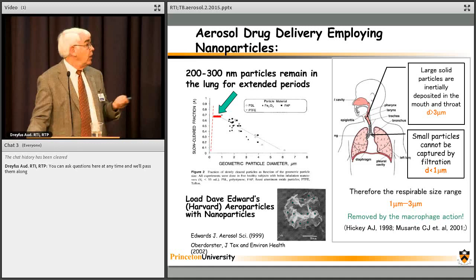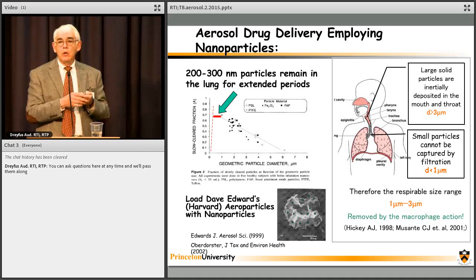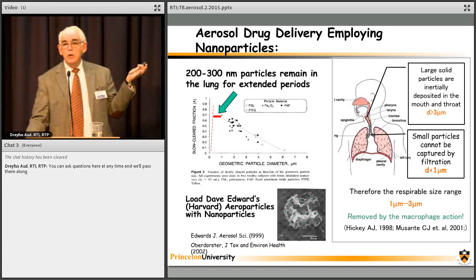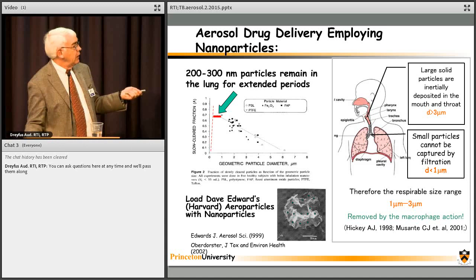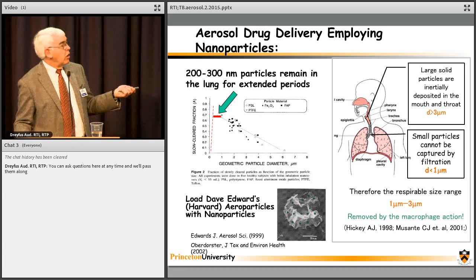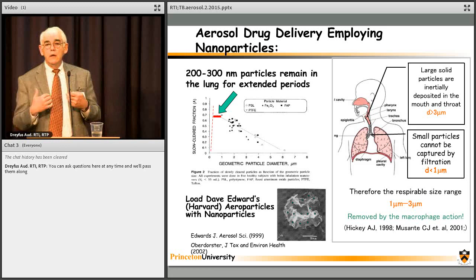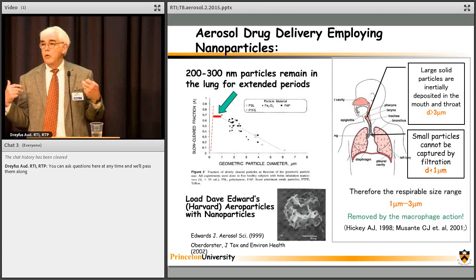How do we get a 1 to 3 micron particle, but how do we get a 100 nanometer particle? The way you do that is you spray dry, and this is Dave Edwards' technology, you spray dry our nanoparticles in with a matrix-forming material to make these crenellated porous particles. So this gives you the larger size. However, it's made from either leucine or mannose. So when it hits the wet lung environment, when it's captured, it immediately dissolves and releases the 100 nanometer particles on the lungs. So this avoids the macrophage recognition by having the immediate dissolution of that larger matrix material.